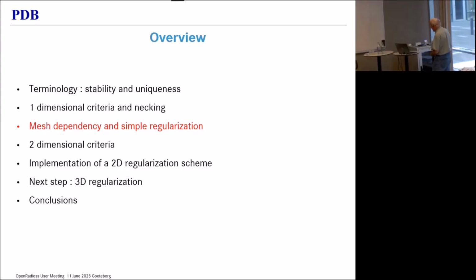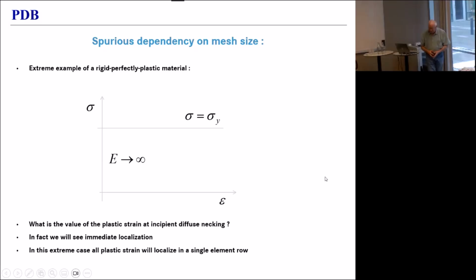So I now come to the mesh dependence. I apologize for the simplicity of this example, but I have to make sure that I get rid of the last bit of doubt about the fact that there is mesh dependency once you reach diffuse necking. Imagine the extremely simplified case of a rigid, perfectly plastic material. So you have a Young's modulus that goes to infinity, and you have a constant yield stress. When do we start necking here? For which plastic strain do we start necking?